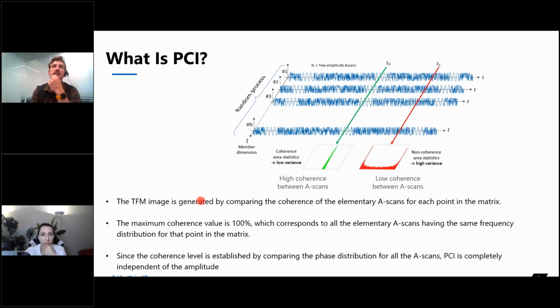This means that we generate an image by comparing the coherence between the A scans, not just the A scans themselves, but by comparing one A scan to another, to another, to another. Because the maximum coherence value is 100%, this means that all the elementary A scans have the same frequency distribution at that point. And this means, once again, that PCI is completely independent of amplitude, because we're only looking at a comparison between the A scans rather than summing all of the amplitude values together.